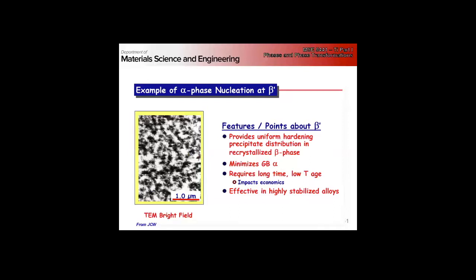Right, we're going to minimize the grain boundary alpha, but this is going to require a long low temperature age, right? The beta prime requires segregation of the beta stabilizing elements away from the beta prime into the matrix. So it requires lower temperatures. That means we need a long time, low temperature age, which makes it economically not the most favorable.